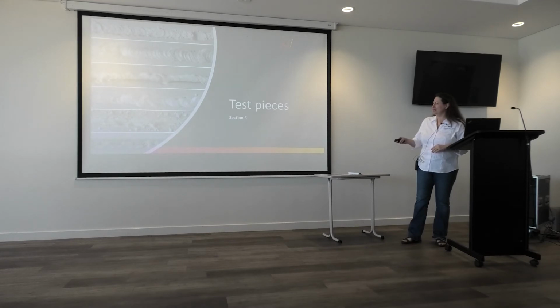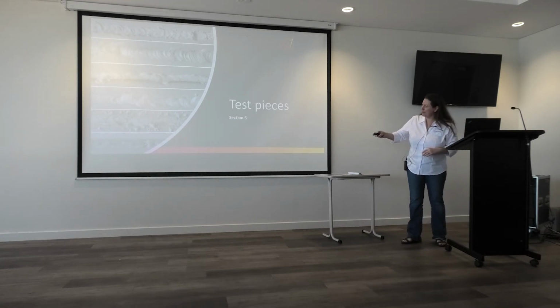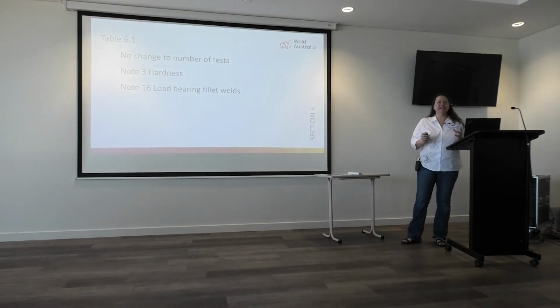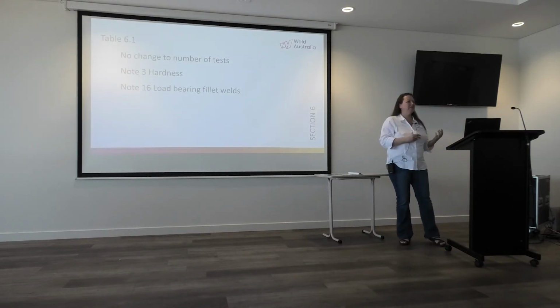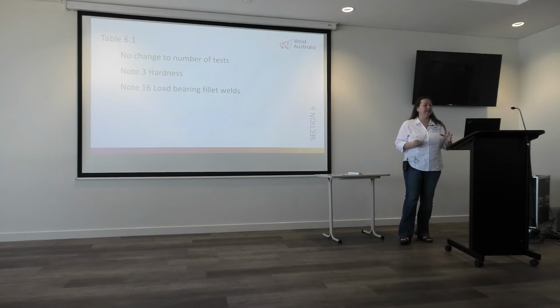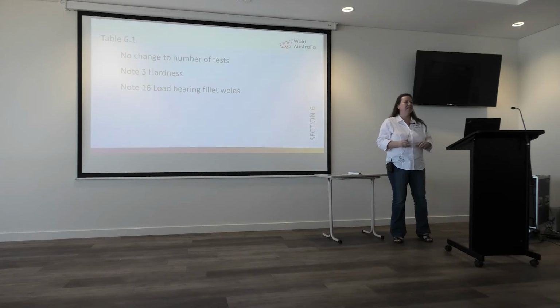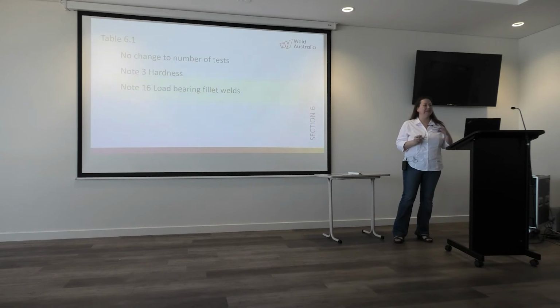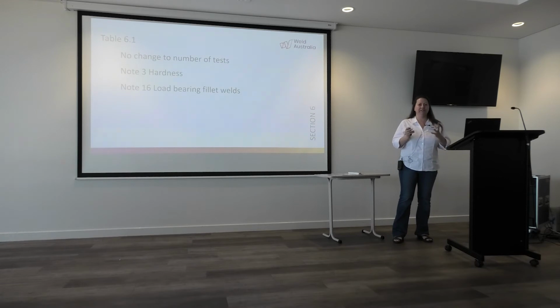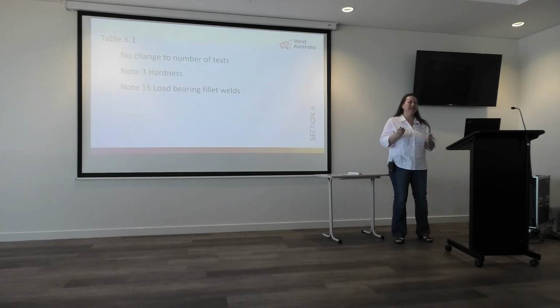So in section 6, test pieces, this is what we're trying to prevent by qualifying. The good thing is that table 6.1 was updated in the previous version with a number of test pieces, so there were no significant changes to that. But note 3 was added with hardness, is that hardness now may become a requirement depending on your application. So we added information around hardness. And then note 16 said that specifically, if you've got a load-bearing fillet weld, these now need to be qualified with a butt weld. So you can't just qualify a fillet weld that's load-bearing, for example, a lug, with just a fillet weld. So that is pretty important because of some failures that happened overseas.